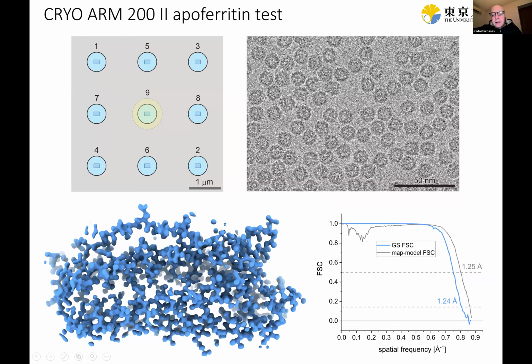With the laser phase plate, if you are able to collect your data perfectly in focus, which in practice is quite challenging actually, it gets exponentially more challenging the higher the resolution you want to achieve. Then in focus with the phase plate, you get doubling of the signal. So theoretically, with the phase plate, you should be able to get better results if you collect the data in focus.